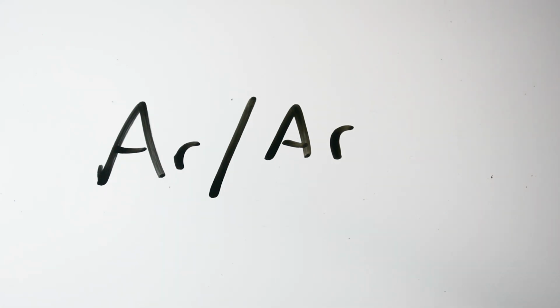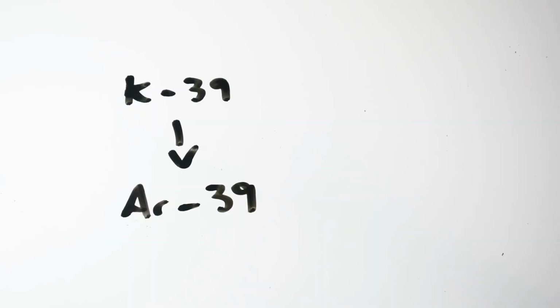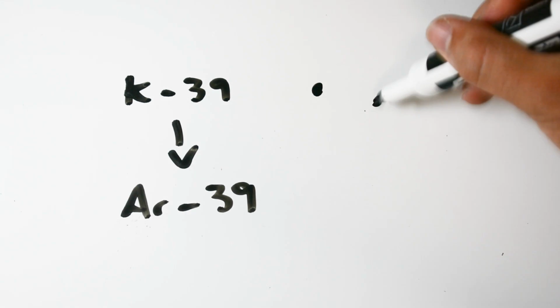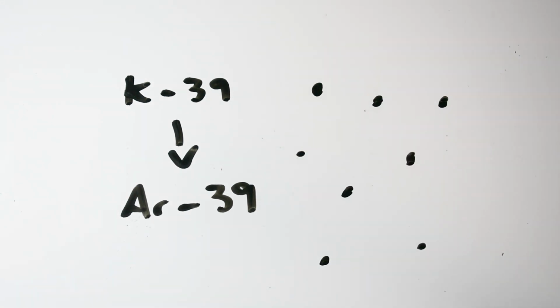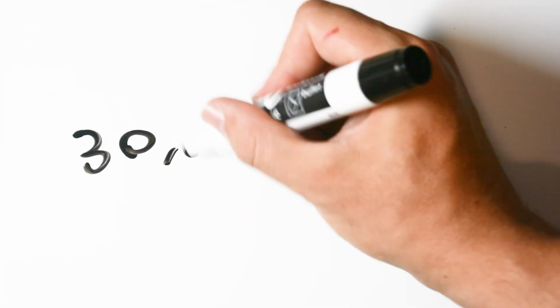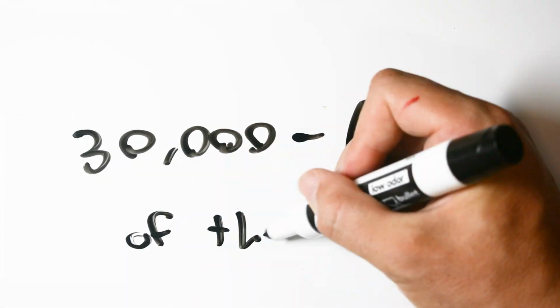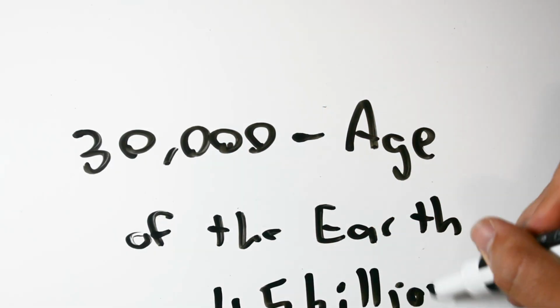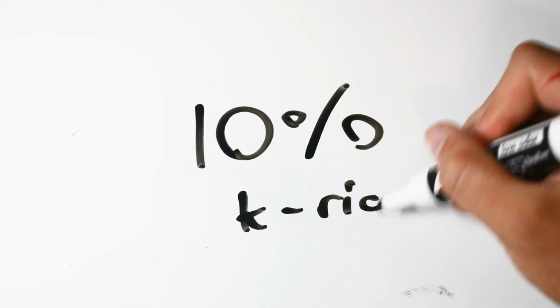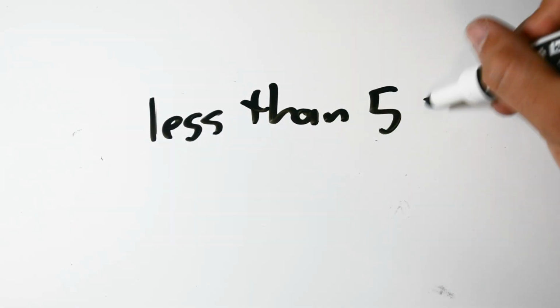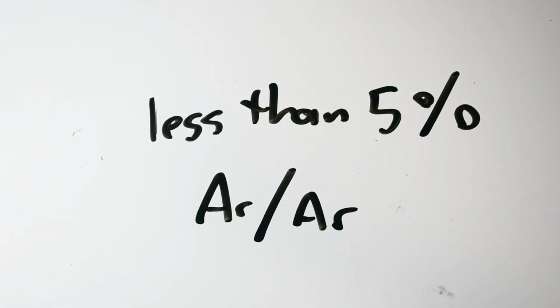But even better than potassium-argon dating is the newer, now more commonly practiced argon-argon dating, where a sample is irradiated to convert a stable isotope, potassium-39, into argon-39 as a proxy for the potassium-40. This method tends to give more precise results and has the ability to target single crystals, thereby reducing the extra noise. These radiometric techniques can be used to date volcanic rock between 30,000 years old to the age of the Earth, dating the exact moment these volcanic rocks were formed to a 10% error margin for potassium-rich samples, with argon-argon dating landing at a higher accuracy of sometimes less than 5%.